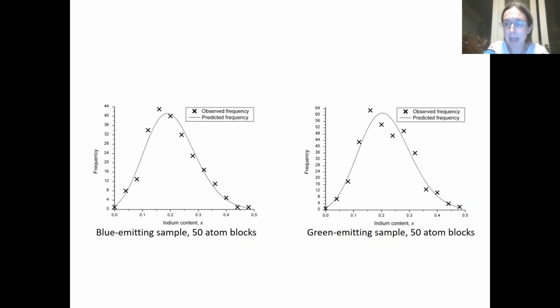Okay? And we expect the compositions of the blocks to vary. We don't expect all of them to be exactly 25% indium because of the nature of randomness, because sometimes we happen in some areas to get a bit more indium or a bit less indium, just like you sometimes happen to roll 10 sixes. Okay, so but we can draw a histogram of how many blocks there are at each indium content. And we know that we'd expect the distribution of the compositions to be binomial.